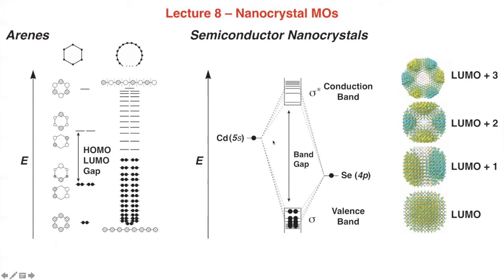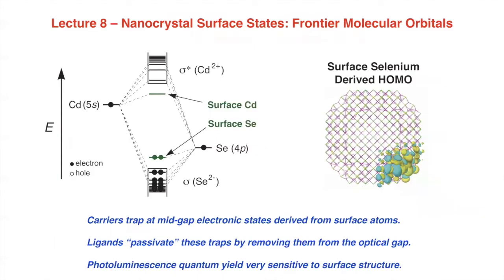And so we've talked a lot about this picture, and for a semiconductor, this kind of all hangs together relatively well. But one of the things that's not illustrated by this diagram are the orbitals that are found at the surfaces of those crystals. So if you consider, a typical cadmium selenide quantum dot might have 10 or 20 or 30 or 40% surface atoms. And those surface atoms don't have the same number of bonds. They have fewer bonding partners. Some of them only make 2 bonds to the underlying crystal. Sometimes they make 3.